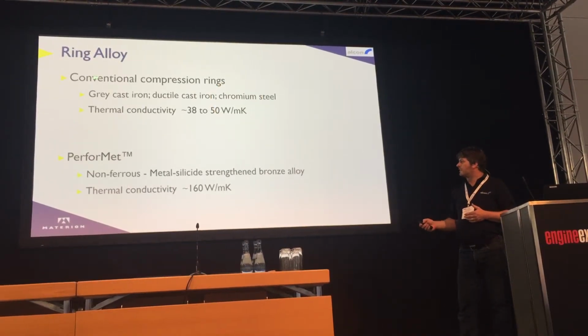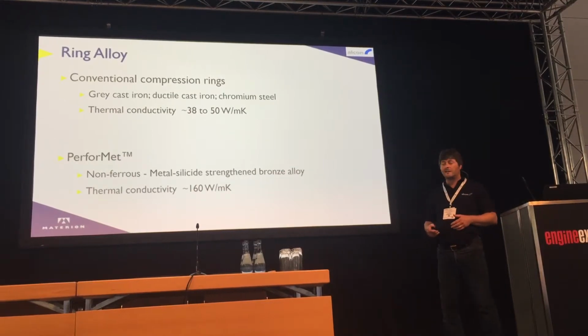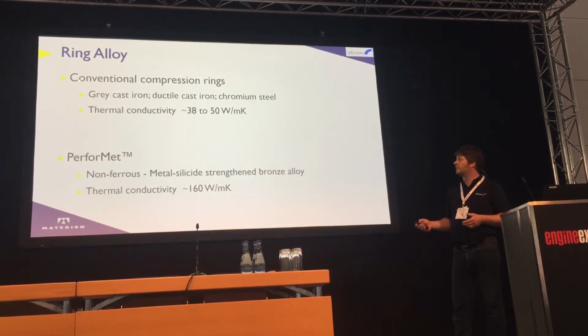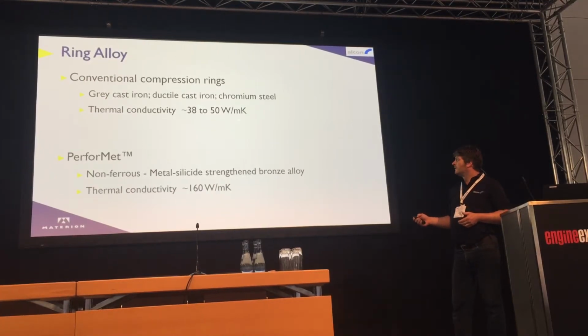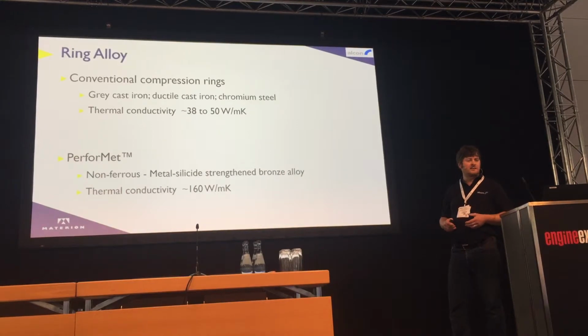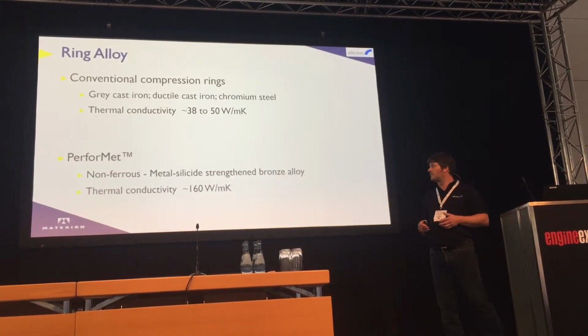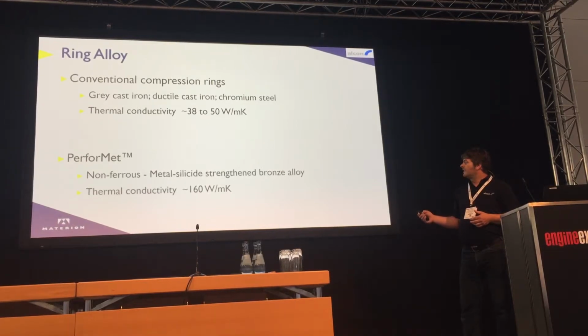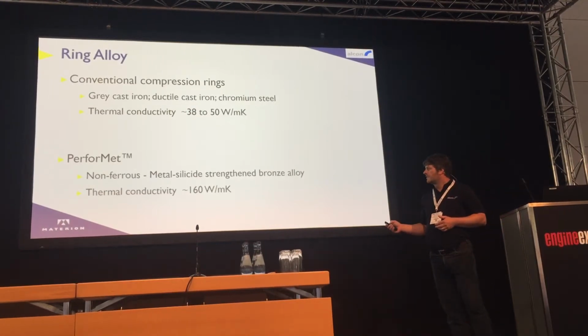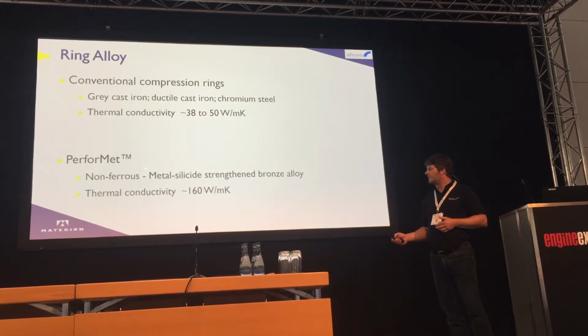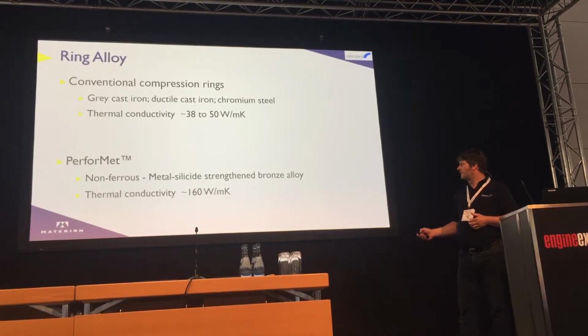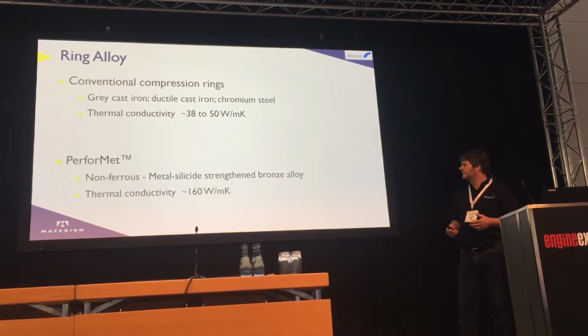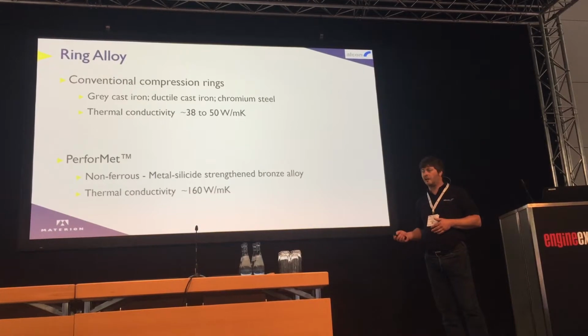So conventional compression rings since the 1850s have been made from cast iron, still a very good material, then moved to ductile cast iron. Most of the high performance engines are running chromium steel rings, titanium nitrided faced rings, chromium nitrided and so on. Thermal conductivity of these rings is around about 38 to 50 watts per meter Kelvin. So Performet is a ring which is non-ferrous. It's a metal silicide strengthened bronze alloy, so it's basically a copper-based alloy. It has a thermal conductivity of 160 watts per meter Kelvin, it's about 4 times that of a conventional ring. And it has very similar mechanical properties in terms of tensile strength and hardness.